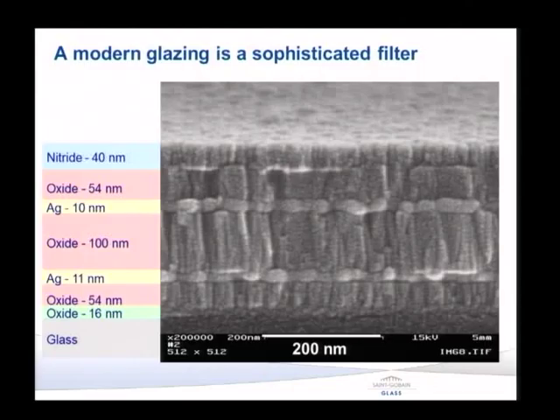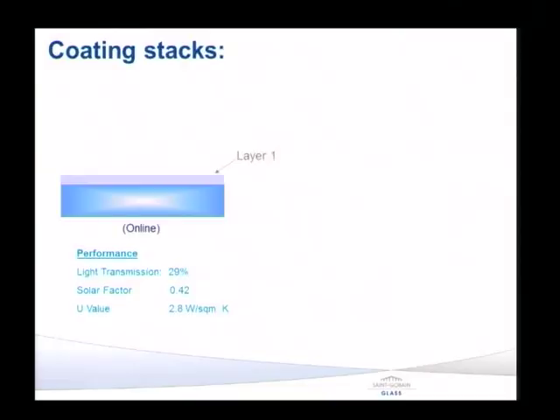This is a coating that is seen under a nanoscope. You can look at the different materials that have been coated on the glass to give you the performance. The performance can be better understood if we compare it with the online coating. Now, in the online coating, a single gas was passed over the glass, which forms a single layer of coating. What happens is this: you have a light transmission of 29, a solar factor of 0.42, which means about 42% of the heat was coming in, and in a double glazing you get a U value of 2.8.